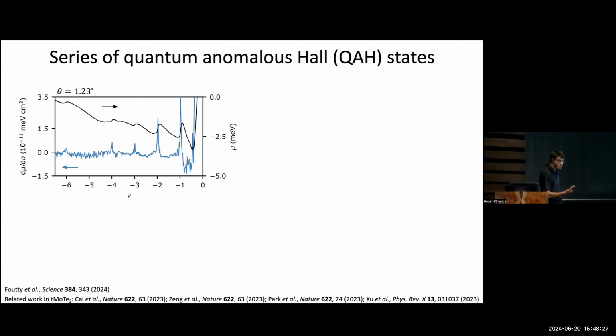And when we measure it with our single electron transistor, what we find is that at integer filling, so this blue is inverse compressibility. So a peak is some gap state. At integer fillings, we see peaks. That is, there is some energy gap opening up. Energy gap at nu equals -1 necessarily, again, is breaking this spin valley symmetry in some way. So this is a broken symmetry state.